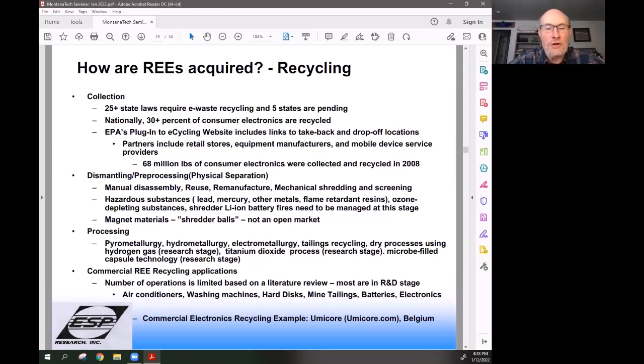There are examples of commercial rare earth recycling going on today. They're tied up with companies like Umicore out of Belgium. They recycle just about anything they can get that has electronics in it. They pull out the platinum group metals and gold and silver, and then they take the rest of the slag off of those valuable metals, and sell that off to a secondary company also in Belgium that then recycles, or purifies and separates, the rare earths for reapplication. So there is recycling going on, but it's very, very limited, and it's pretty hard to get done because of the cost.